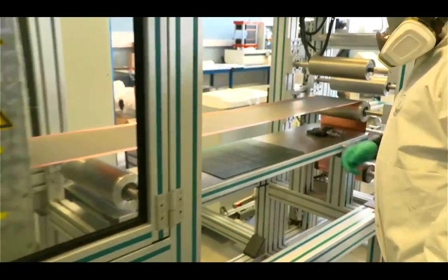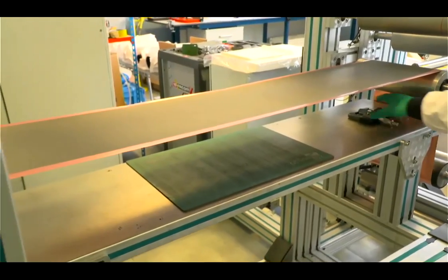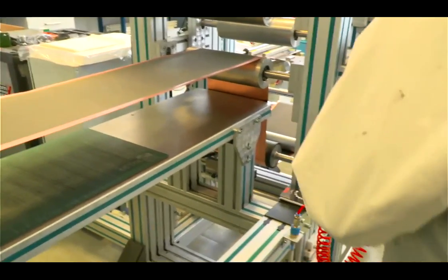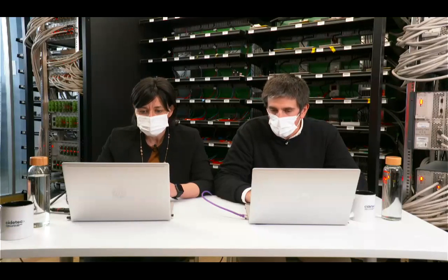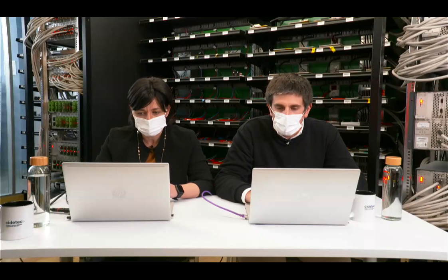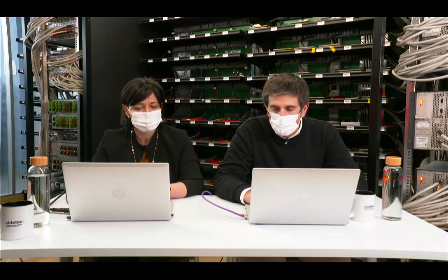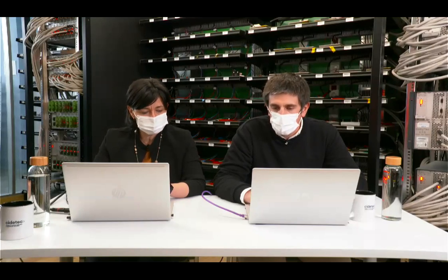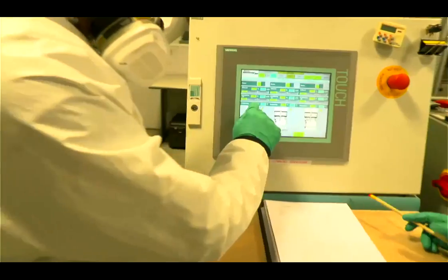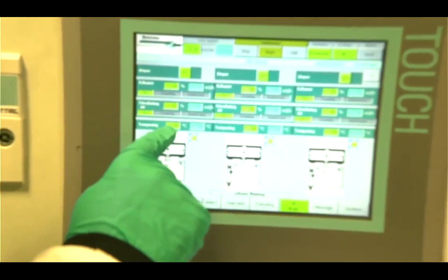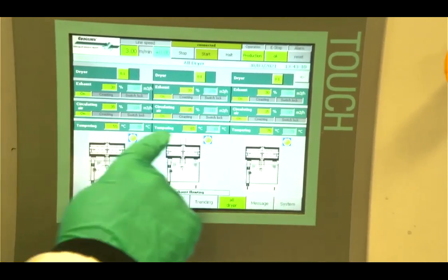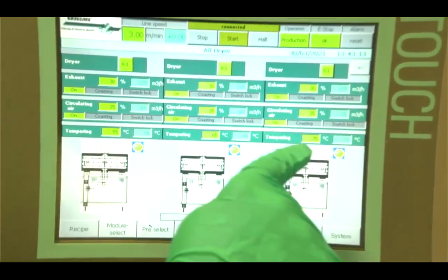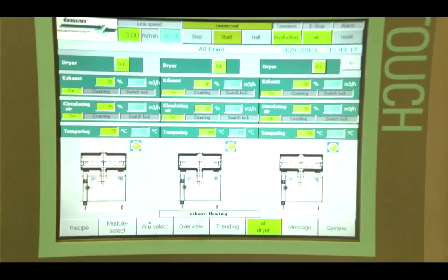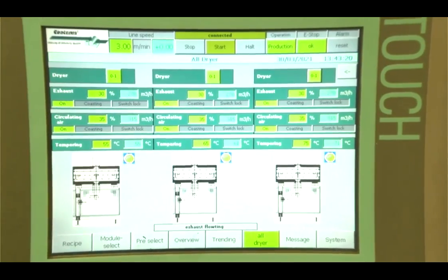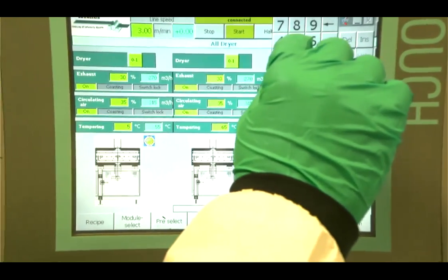Yeah, and regarding these questions, there is also the drying temperature that we usually use in the ovens. As Idoia mentioned, for example, with graphite and the loadings that we are targeting, we have the experience that using a ramp works, for example, with a lower temperature at the beginning in the first oven, just to start with an easier drying and in order to not damage the electrode. And for the last step, in the third oven, is where we use the higher temperature.